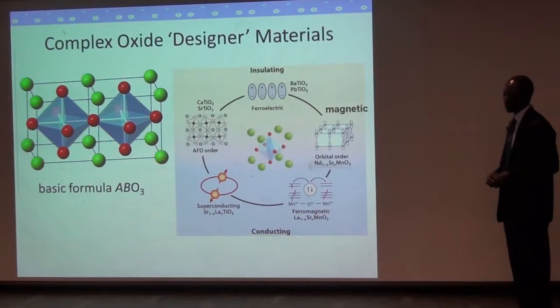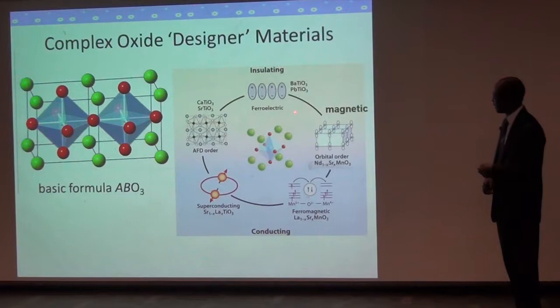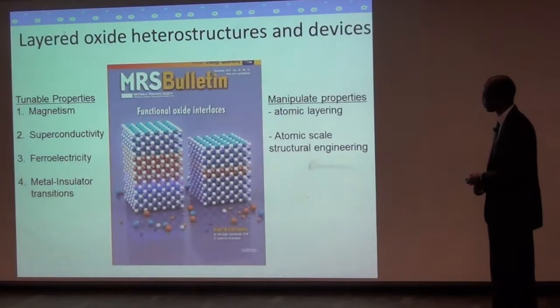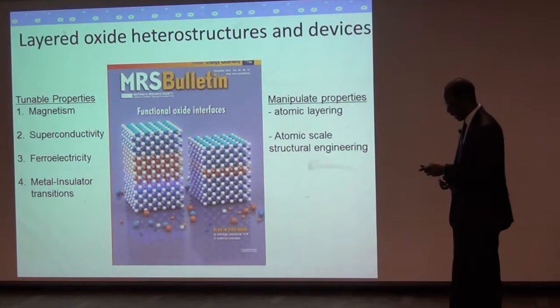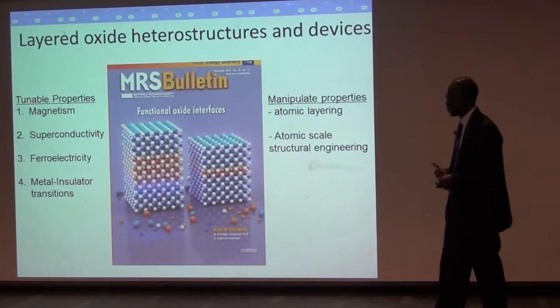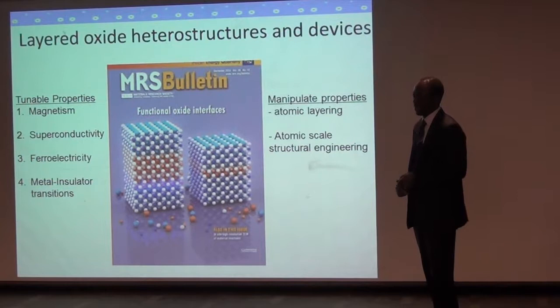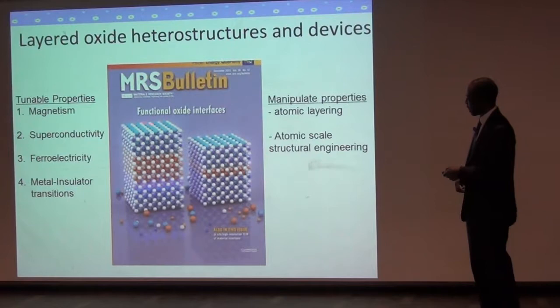I refer to these materials as designer materials because you can get almost any physical property you want in condensed matter physics by simply changing the different metals or the chemistry, or by inducing very small distortions in the way these oxygen atoms sit relative to the rest of the structure. Some examples include barium titanate, which is insulating and piezoelectric, whereas you can also change the chemistry to get materials which are magnetic and superconducting. Complex oxides are exciting because since they all have very similar crystal structures, you can envision stacking layers of different materials with different properties to make new devices or to get new physics.